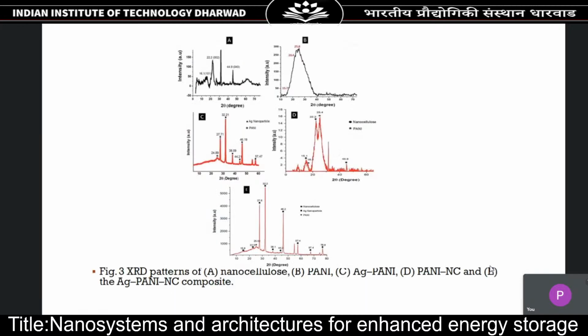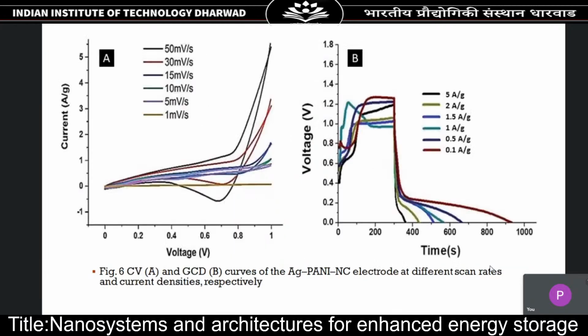We carried out XRD of the different subconstituents. We carried out XRD of nanocellulose, then polyaniline, then silver polyaniline, then polyaniline and nanocellulose, and finally the composite. You can see the cyclic voltammetry and the charge discharge curves of the composite. This composite has silver, polyaniline, and nanocellulose. You can see that the study was done at different scan rates and also for different current densities.